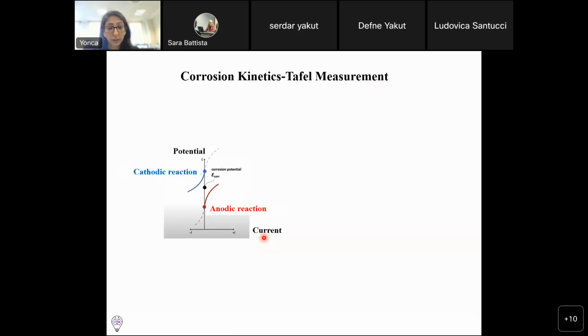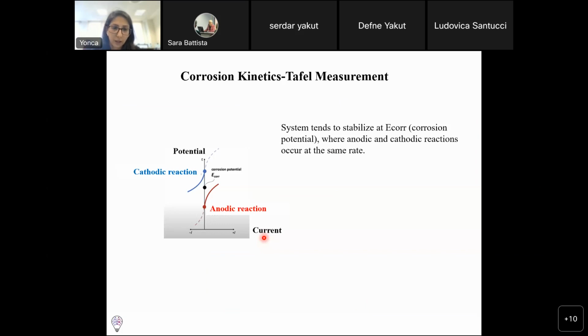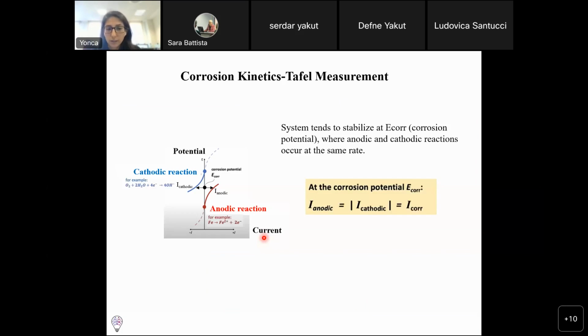So you need the anodic and the cathodic reaction. Once you have an anodic and cathodic reaction, you can plot it in a current versus potential graph. At the corrosion potential, the anodic and the cathodic reactions tend to have the same rate. So at the corrosion potential, the anodic and the cathodic currents are equal to each other, which gives the corrosion potential. Let's say you have iron, it's going to oxidize in the anodic reaction, and in the cathodic part you will have oxygen, and it will be reduced to OH.